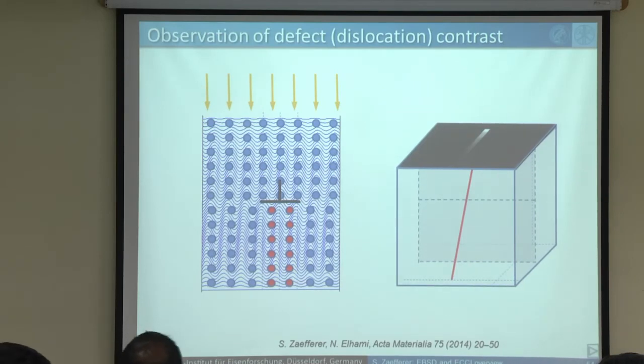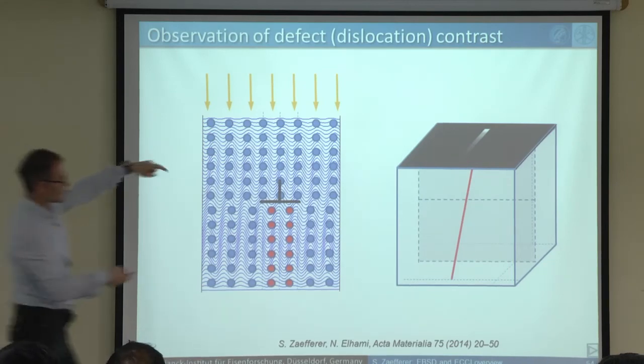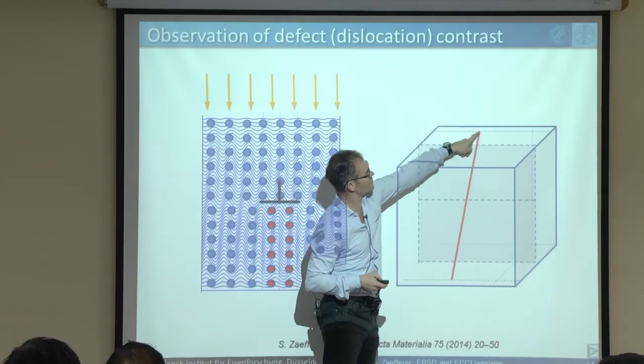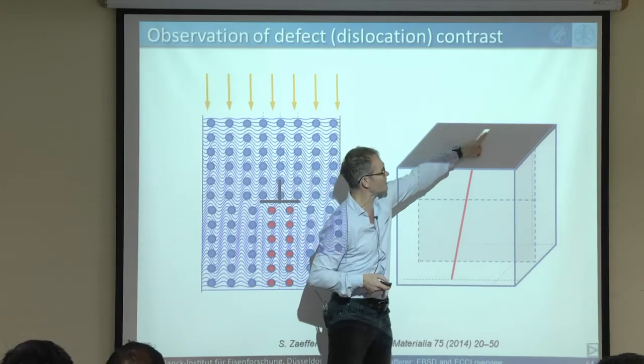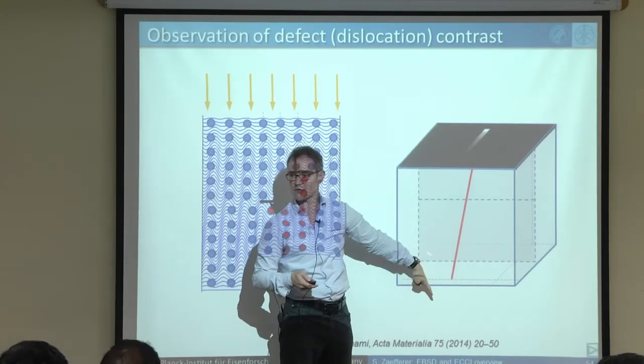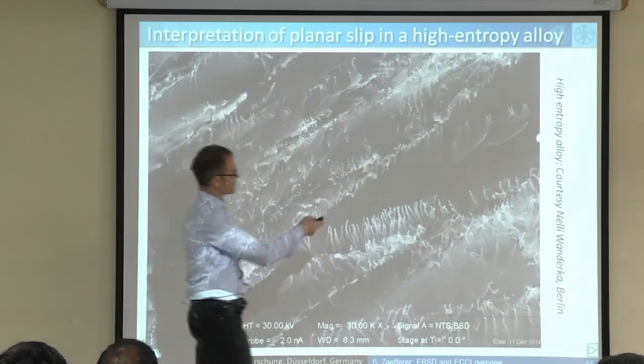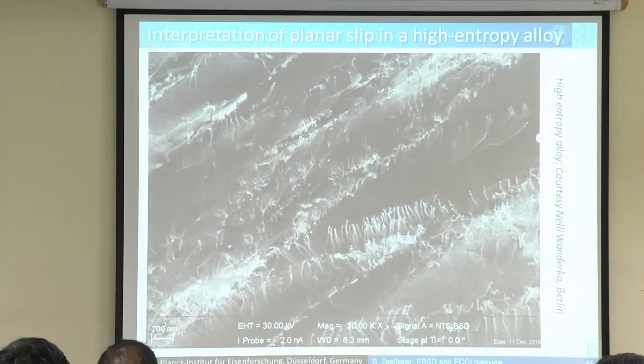So if we look from the top, we will see the dislocation as a white line on an otherwise black area. And of course, where the dislocation comes to the surface, the signal is strongest, and the deeper it is below the surface, the weaker it is. So we see in principle such a picture. And that is a typical picture from a high entropy alloy, which actually shows a lot of very interesting features.